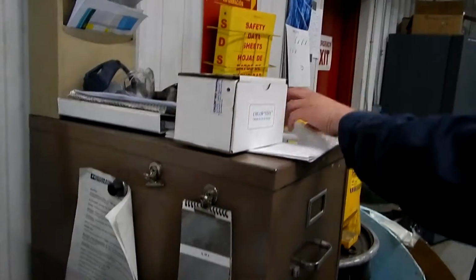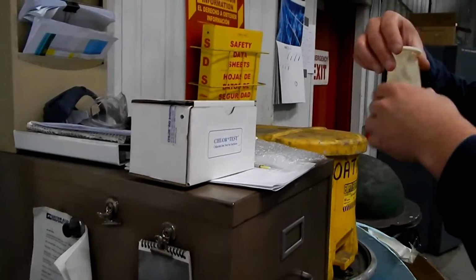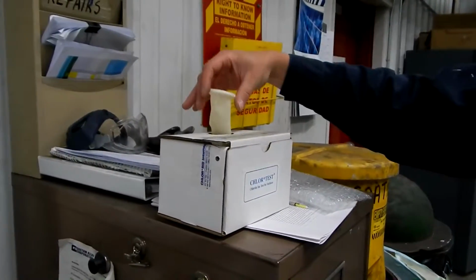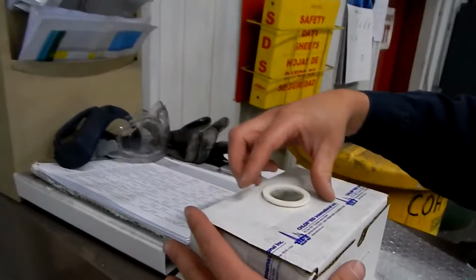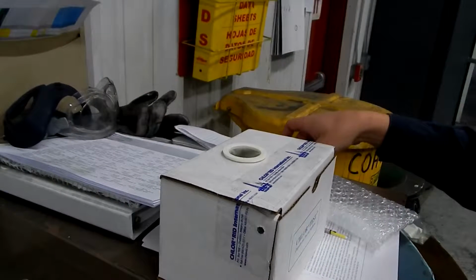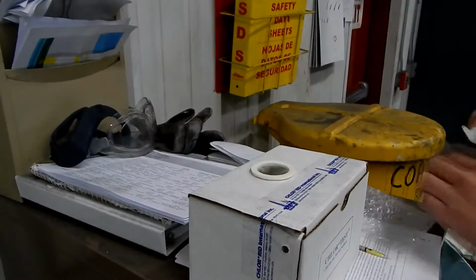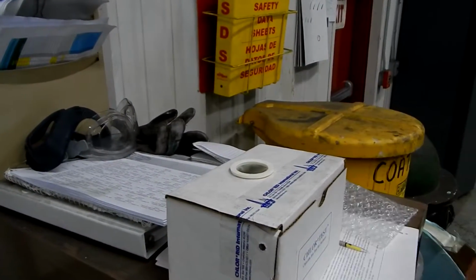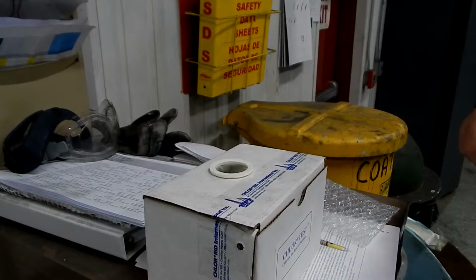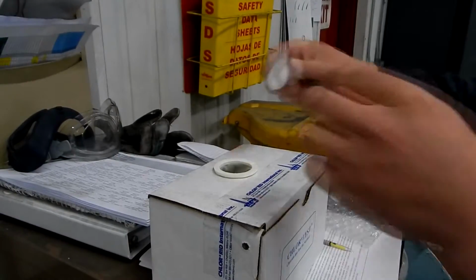In this case, the ID needs to be compared to the receiver to make sure they match. Step 7. Perform surface chloride test. First, open the box located in the storage cabinet and remove a testing pouch. Open the pouch and make sure all pieces are included. There should be a glass tube, a black rubber top, a tan pouch, a chloride extract, and a metal piece. Once you have ensured that you have all the pieces, open the chloride extract and pour all of it into the opening of the tan pouch.